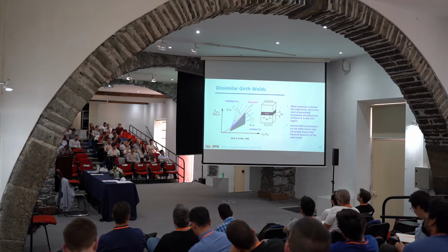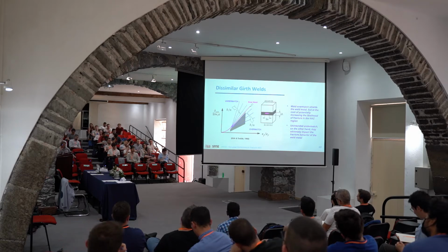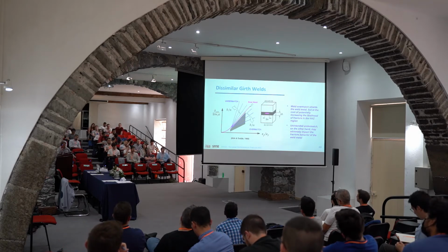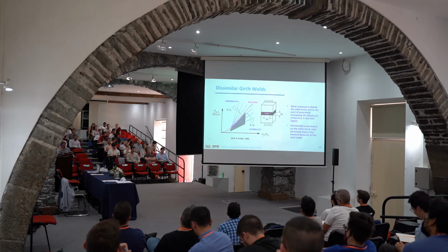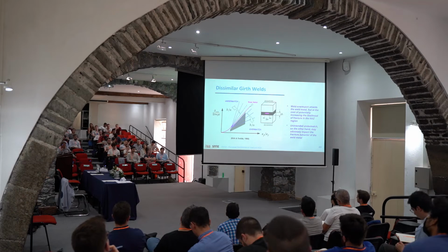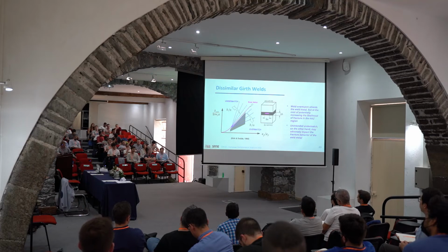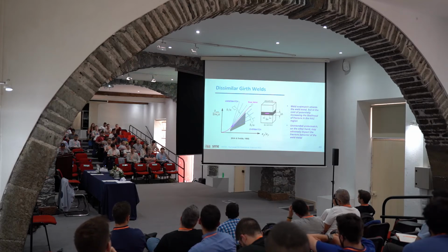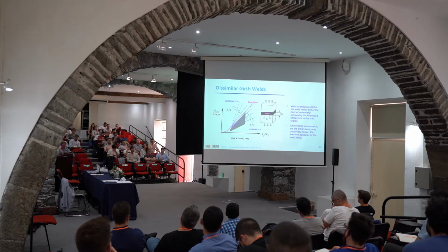The dissimilar girth also has an effect on the ECA methodology. Okay? As you can see here in a very simplified way, this is a simplified representation of the critical CTOD normalized by the crack size and the yield strain, and here is the remote strain normalized by the yield strain. Okay? You can see here that if you have overmatch or undermatch, you are moving your, let's say, design curve to the left or to the right.